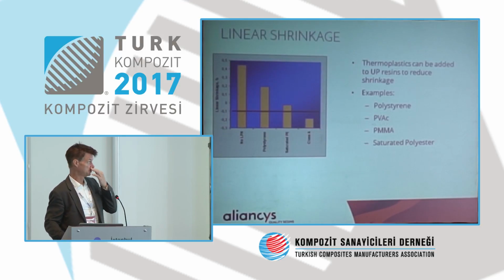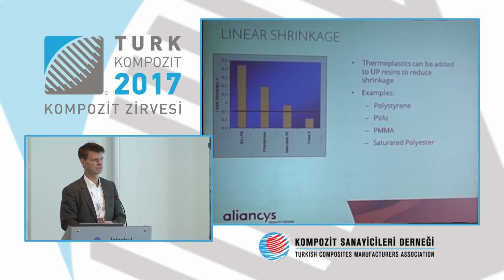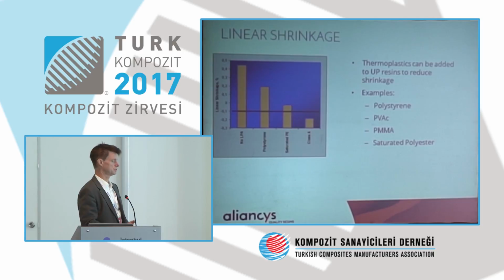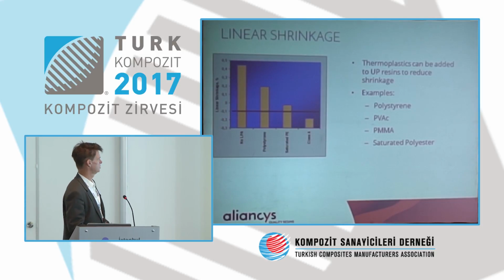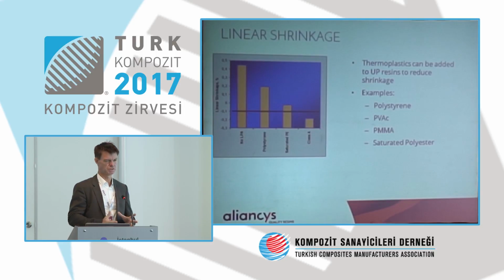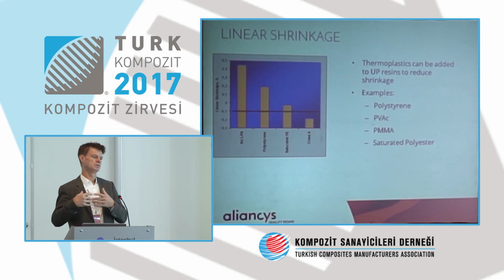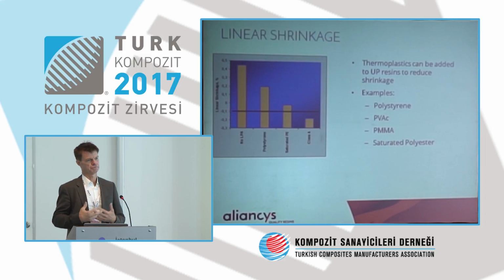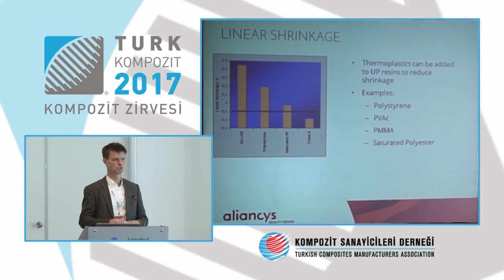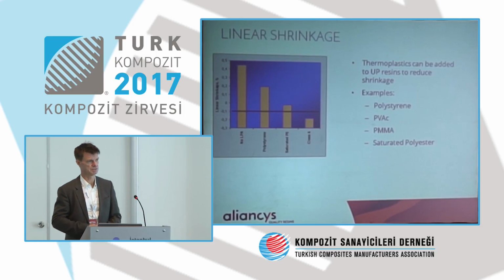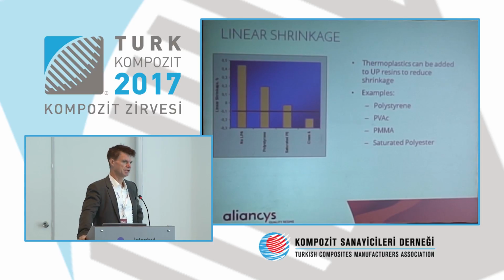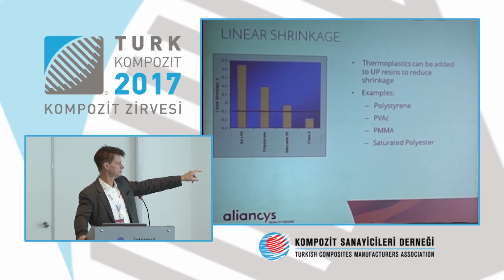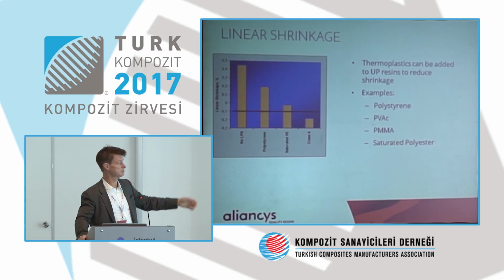As I said before, shrinkage is a very important parameter. We have a material, SMC, which intrinsically has a shrinkage, and we have to compensate this shrinkage. How to do that? Basically, we have different components. There's a base resin with a certain shrinkage, and we can compensate it by using so-called low-profile additives, LPA. And these LPAs consist of polystyrene, PVAC, which is a thermoplastic solution, or PMMA, which is also a thermoplastic solution.